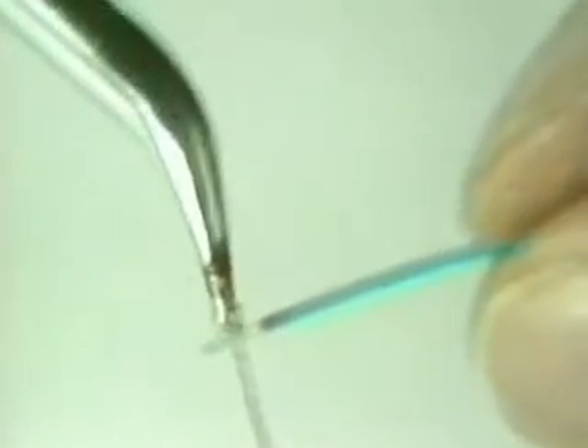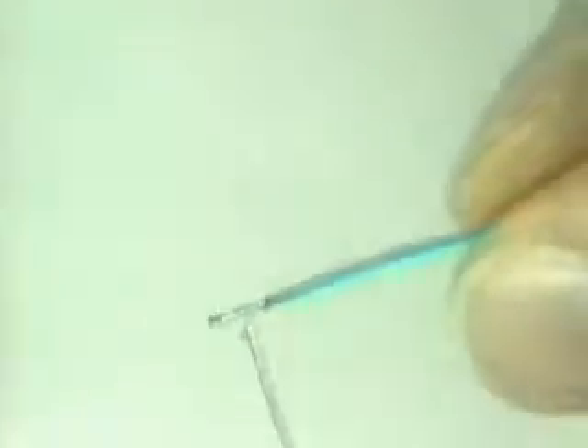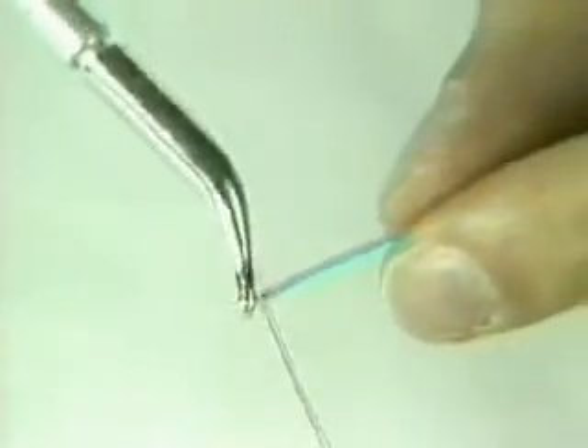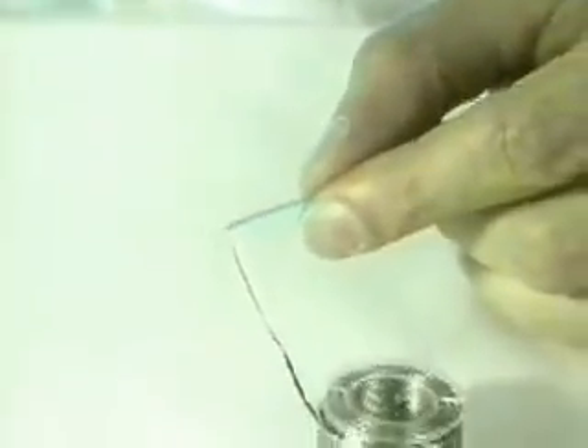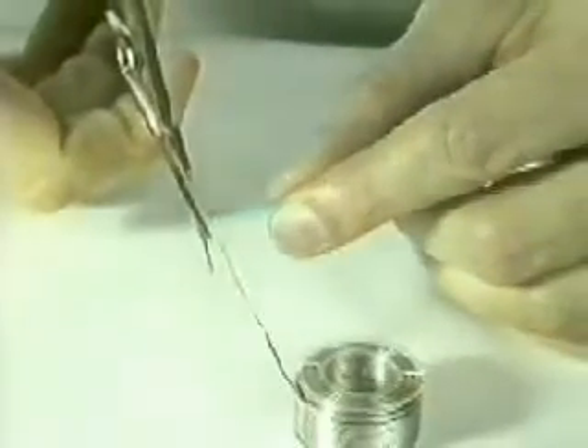When tinning the ends of the cores in the lead, the solder must be so fed that flux contained in it can transfer to the core. It's only then that the solder can flow properly.